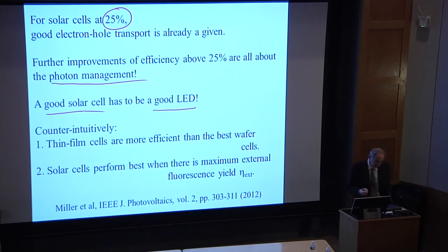Right now, I want to point out that this is somewhat counterintuitive because everyone has always said the best solar cell is a wafer solar cell, and then a thin film cell is cheaper, but it's not as good. And that's the assumption. But as you can see here, these thin film cells are actually better than the best wafer cell. In fact, it did not achieve the record until it was peeled from the wafer. So that's counterintuitive to those people who have been steeped in the tradition of this field. Then the second thing that's extremely counterintuitive is why should a solar cell give any photons back? And it says give back some photons. It's not just charity, it's actually needed to achieve the world record.